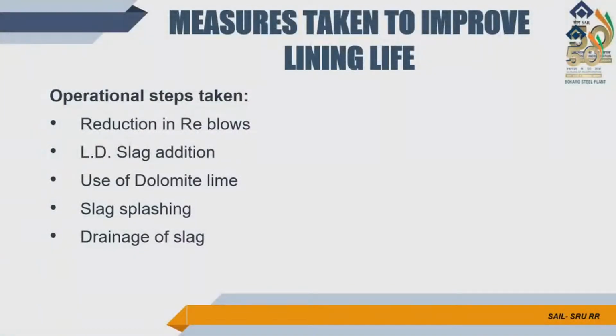Reblows are a thing of the past. So LD slag addition was done. Dolomite lime was done. Slag splashing was done, and drainage of slag through tap hole was done, just to try that we can increase the life of the refractories around the tap hole sleeve. We have drainage of some slag from tap hole.